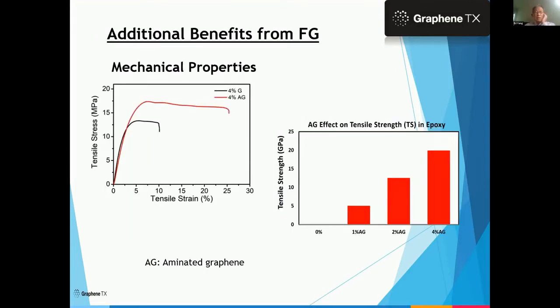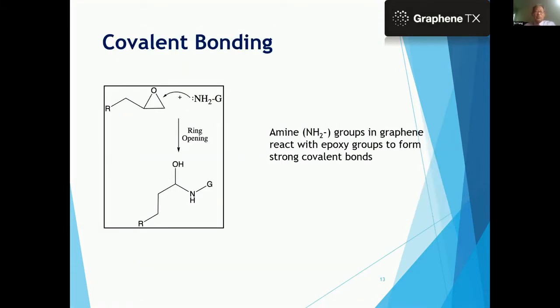And then there are additional benefits from functionalized graphene. As you can see from the left graph, the pristine graphene shows poorer, lower tensile strength compared to aminated graphene, and also the right-hand side graph shows that as you add more, it will increase the mechanical property. And then the question is why? If you just use pristine graphene, it is just a physical mixing. There is no chemical bonding between graphene and epoxy. But if you use aminated graphene, the amine group reacts with the epoxy group, and there is a ring opening, and then it forms a carbon and nitrogen bond. So it will give you a strong chemical bond we call a covalent bond. That's why it enhances mechanical properties.